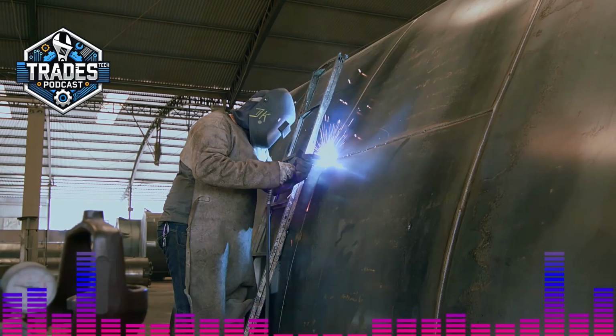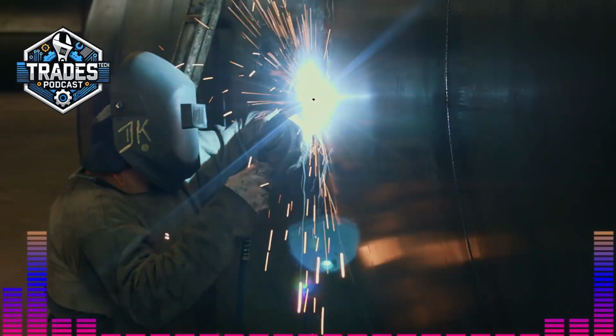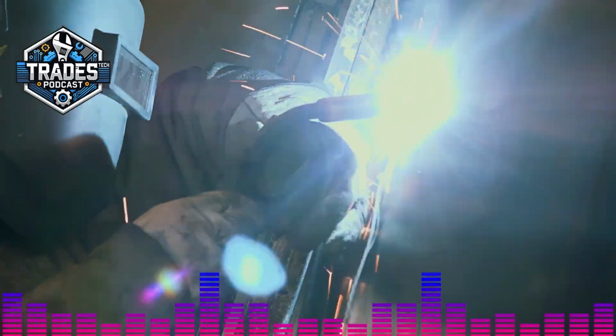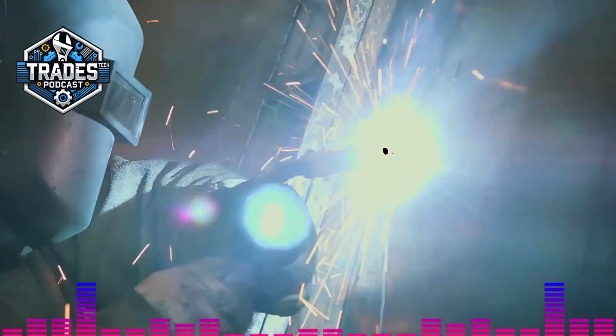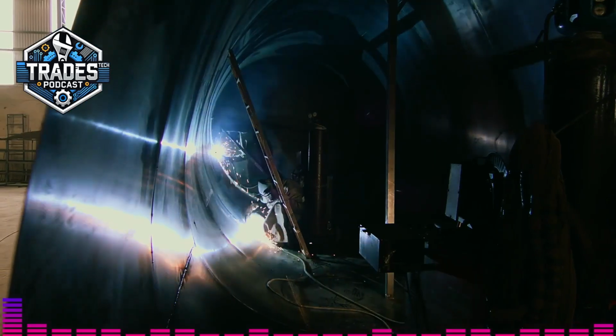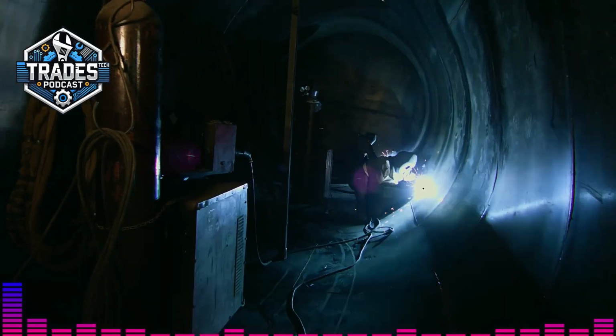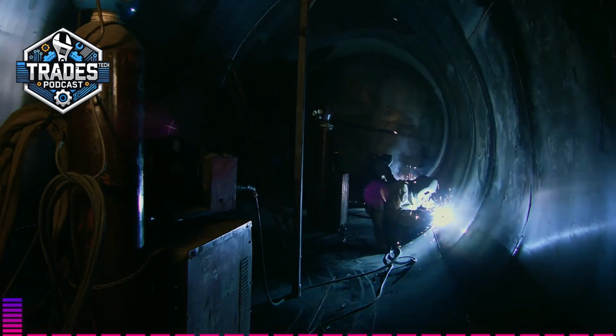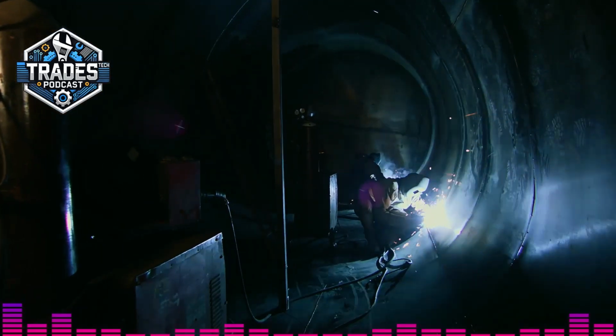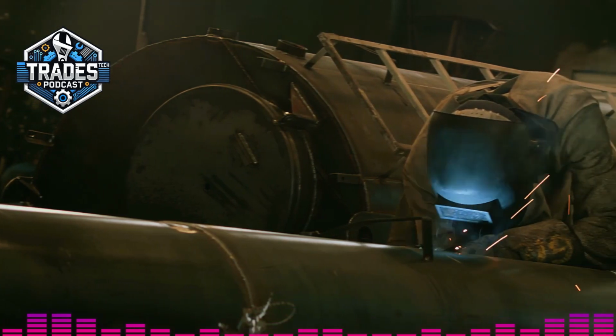Exactly. The second type is dual-shielded FCAW, or FCAW-G. This process uses the flux-core for things like fluxing agents and deoxidizers, but it also requires an external shielding gas, typically a mix of argon and CO2, similar to what you'd use for MIG welding on steel. The best of both worlds in a way, combining the flux benefits with gas shielding. That's a good way to think about it. The choice between self-shielded and dual-shielded depends heavily on the specific application, materials, and environmental conditions.